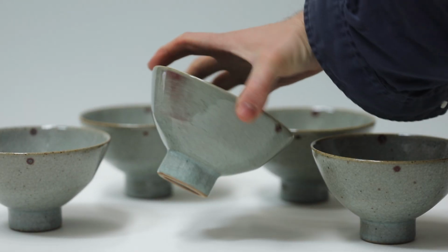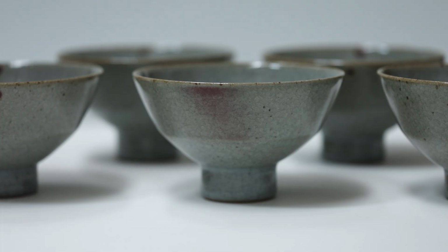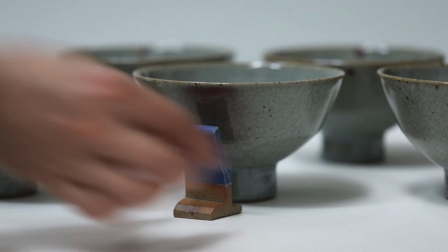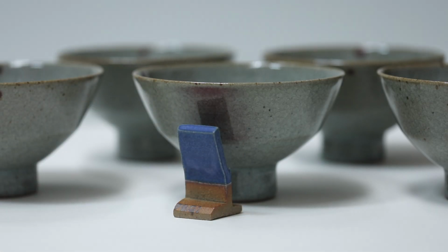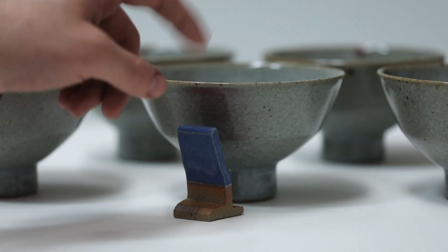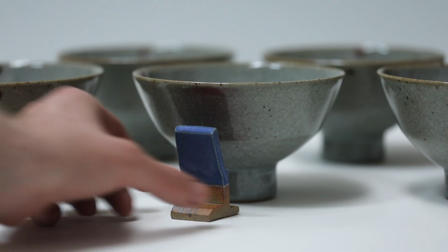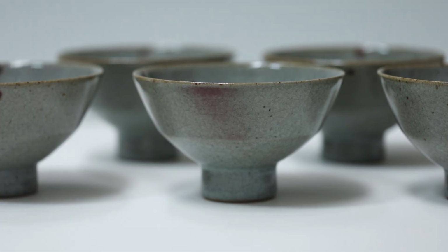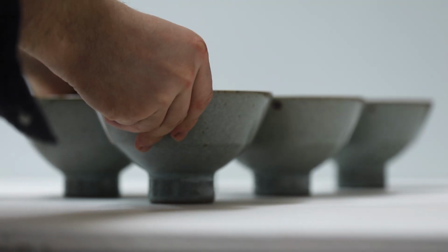Due to all the blue test tiles you might have seen, which I fired alongside these bowls, one of them had this lovely red flash on one side, caused by copper carbonate, one of the recipes included. Although unusually, this was the only bowl affected, despite there being a number of tiles in the kiln with copper in them. But it's got me thinking maybe I could place small copper glazed objects around the firing to purposefully create really subtle red blushes like this.